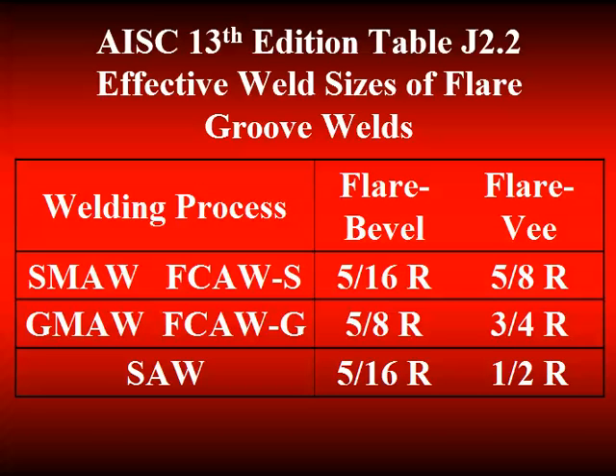With gas metal arc, gas shielded flux core, because these exhibit more penetration in that type of joint, notice we get twice as much throat if we fillet flush. So here we're at 5/8 R and 3/4 R, and there we have the values for submerged arc. That's if we fillet flush. If we don't fillet, we have an X dimension. Take this value, assume I did fillet, subtract off the X dimension that you're not going to fill, and that's what you would use for the throat.